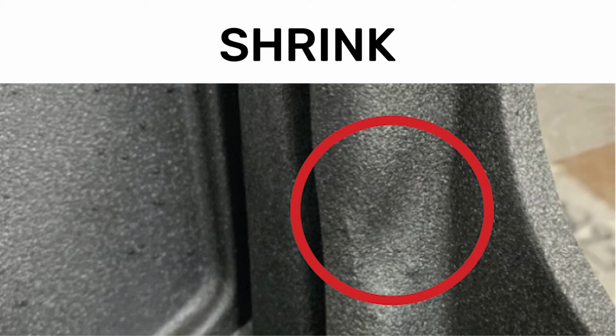Shrink is more likely to happen if you have a really thick section in comparison to the rest of your part, so prevent shrink by designing gradual changes in your wall thickness, or work with your caster to find a way to send the shrink into the gating instead of into your part. The gating just gets sawed off anyway.